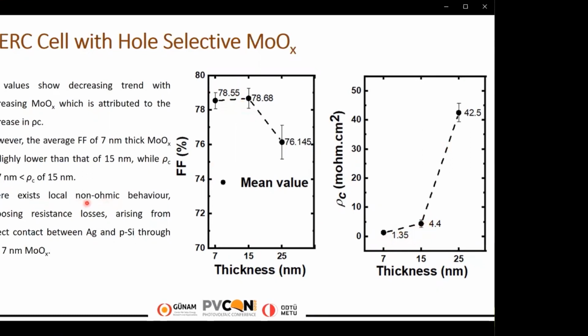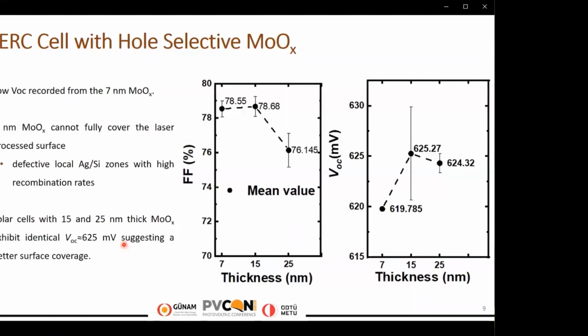This suggests there exists local non-ohmic behavior imposing resistance losses arising from the direct contact between silver and p-type silicon through 7 nanometer molybdenum oxide. And this is in line with the low VOC reported from 7 nanometer molybdenum oxide. And 7 nanometer molybdenum oxide cannot fully cover the laser processed surface, resulting in defective local silver silicon zones with high recombination rates. And PERC solar cells with 15 and 25 nanometer thick molybdenum oxide exhibit identical VOC values of around 625 millivolts, suggesting better surface coverage for these thicknesses.